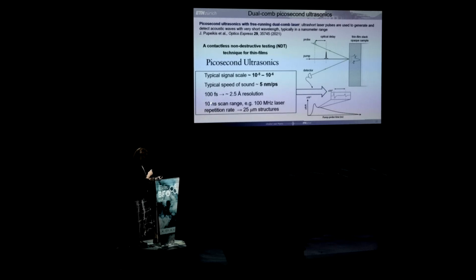So if you have, for example, a 100 megahertz laser, you have a scan range before the next pump pulse comes again of 10 nanosecond, which lets you look at these multi-layer stacks of 25 micrometer with really high accuracy. So there is a huge interest in this picosecond ultrasonics in the semiconductor industry for non-destructive testing of these layer stacks. And we just saw examples before.